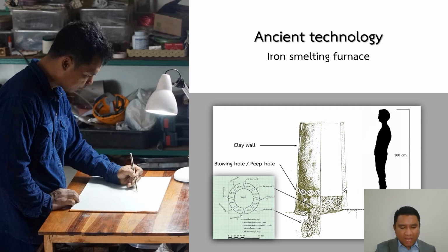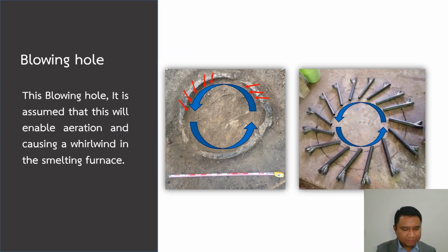Second, to make an assumption about the shape of the product that we obtain from the ancient iron smelting site in Loei Basin, northern Thailand. The question of this study starts from the discovery of an iron smelting furnace still in situ, with a blowing hole cone-shaped diagonally to the wall of the furnace at 30 to 45 degrees, showing the intention of causing a whirlwind in the smelting furnace. From this, what were the factors that resulted in the ancient iron smelting process?